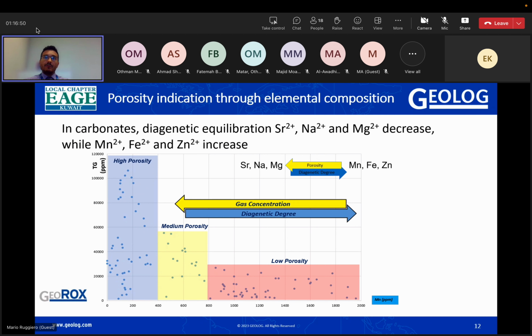So you expect when you have higher strontium, sodium, and magnesium, statistically to have higher porosity, so higher gas from mud. And while you have higher diagenesis, you see these markers like manganese, iron, and zinc, very abundant, and you expect to have lower porosity.